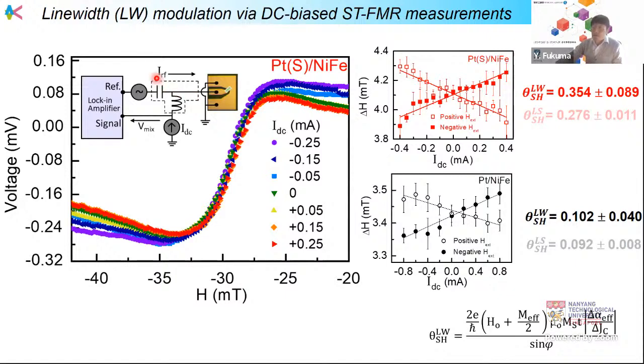We can also confirm the spin Hall effect by using this kind of modulation of the spectra. As you know, we can control magnetization dynamics by using the spin orbit torque. In this measurement, we apply microwaves to the sample and excite the ferromagnetic resonance. This ferromagnetic resonance is tuned by applying a DC current, and the spectral line width is modulated by applying the DC current. When we apply a positive magnetic field and the opposite magnetic field, they show opposite behavior. That's why we can say this modulation is caused by the spin Hall effect.